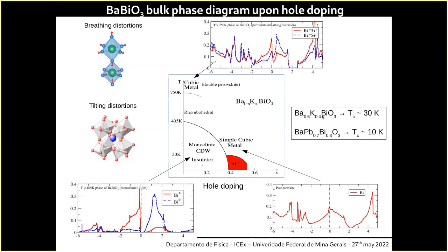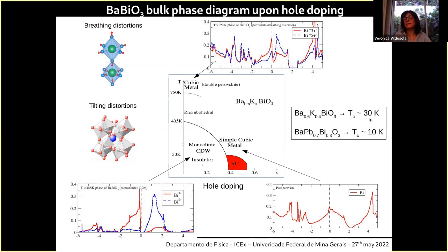When the system is doped with potassium at the barium oxygen plane, the superconductivity can be obtained below 30 Kelvin, 32, and when it is doped with lead at the bismuth oxygen plane, the critical temperature is lower, but it can be as high as 10 Kelvins. And here you can see the corresponding density of states of the normal phase, where you have the S band with the Fermi level more shifted to the left because it is hole doped. But you have only one type of band. It is not charge disproportionated anymore.